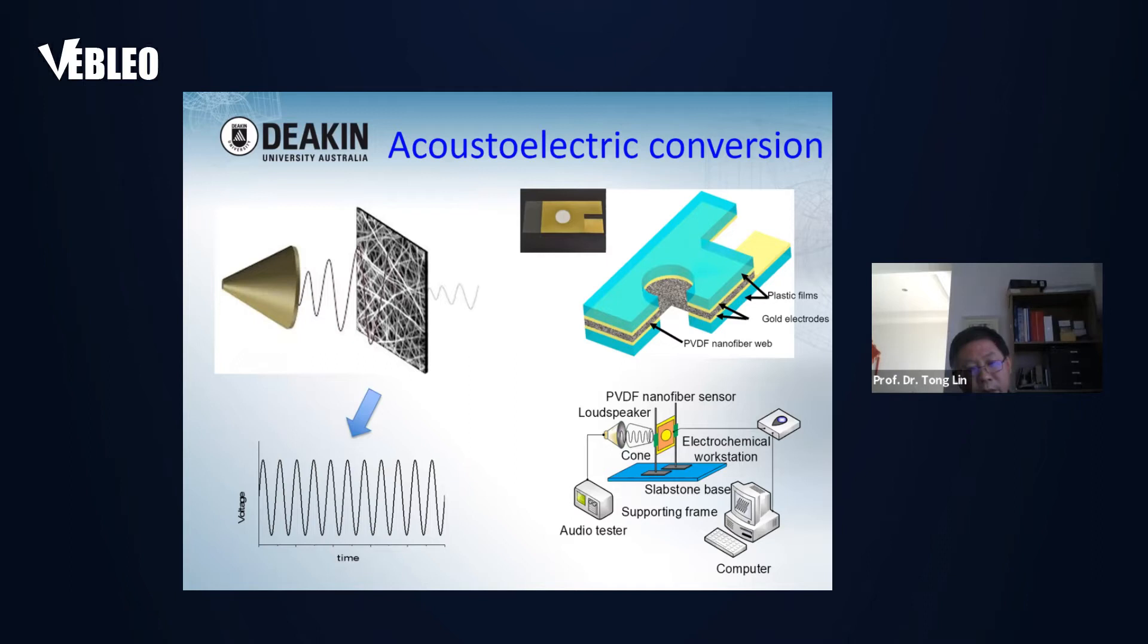Because nanofiber is a good sound absorber, we saw that if we can combine nanofiber sound-absorbing property with piezoelectric property, we may be able to use sound as an energy source to generate electrical power. Indeed, we achieved this by using a very simple device. The right image shows a device structure we developed. It includes three layers. The middle layer is nanofiber. Two outer layers are plastic film with a layer of gold on the inner side functioning as electrodes. The electrode has a large hole in the middle that allows the nanofiber to directly interact with the sound.